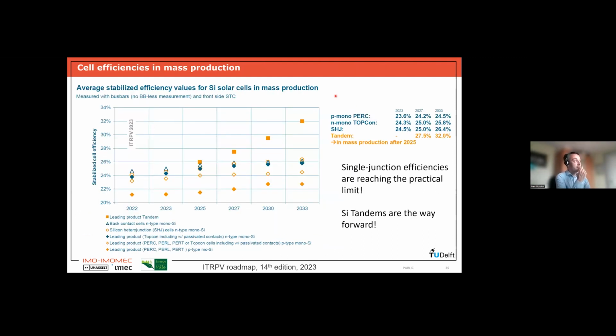Then we can also look at the cell efficiencies that we have now in mass production. So these are, let's say, the best cell efficiencies in mass production currently. So if we look at PERC cells, we are around 23.5%. So these are the best in class efficiencies. For TOPCon and silicon heterojunction, we are actually a little bit higher, already above 24%. So the prediction of the industry is that all these cell efficiencies in industry in the next 10 years will be substantially increased. And for the passivated contacts, we will probably reach 25 or 26%. So it's even higher than what we predicted in the past in this roadmap.